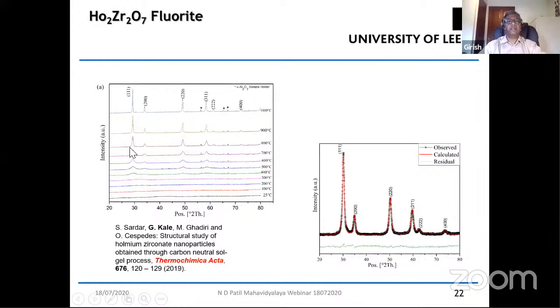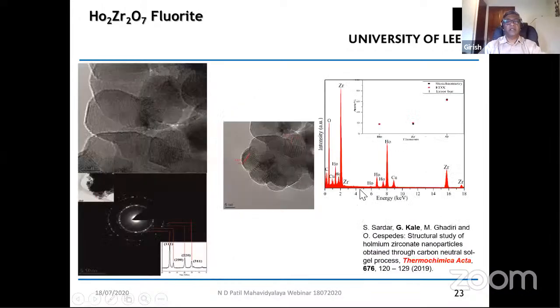But as the temperature increases, you can see that the peaks get sharper and sharper. And of course, we did some Rietveld refinement as well to prove that there are no impurity phases. So this particular composition is a fully crystalline phase produced at about 500 degrees Celsius in the form of nanoparticles.